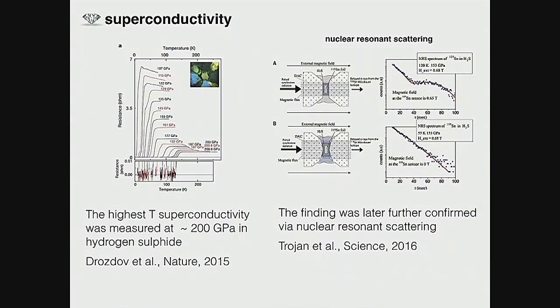So I'll show you now a few very recent highlights, very groundbreaking results in high pressure science. A couple of years ago, this group from Germany finally reached this superconductivity. High pressure superconductivity has been predicted for a very long time, and this group managed to actually obtain measurements of superconductivity, at very high temperature, around 200 Kelvin at roughly 200 GPa.